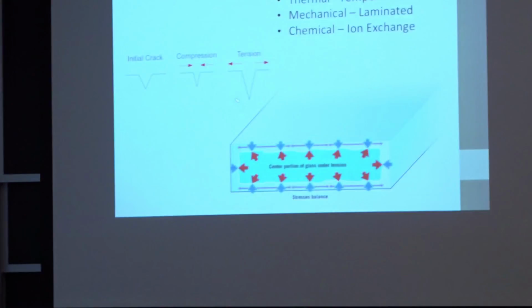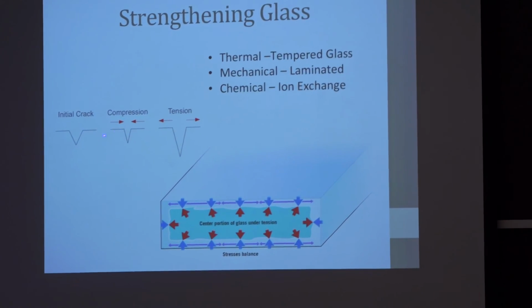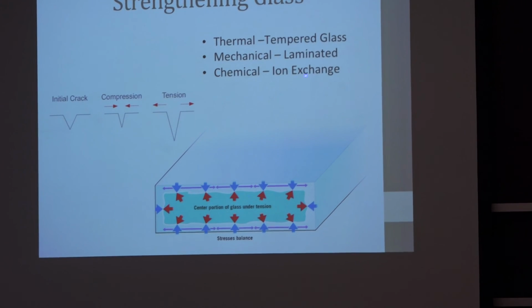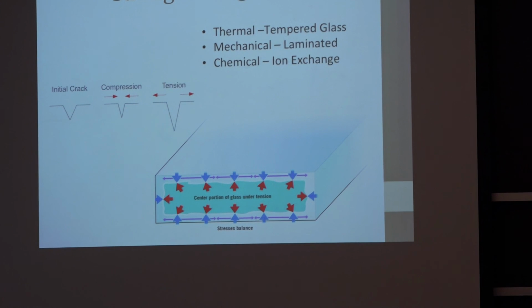I will bet you money this is at least 3 layers. Just like Corning ware, the cookware, it's 3 layers of glass. It's a laminated glass. Top layer and bottom layer like a peanut butter sandwich. The middle layer is going to be a different coefficient of expansion. When you pull these things off like a plate glass manufacturer, just rolls of these sheets of glass, put them together, 3 layers, you end up with, when you cool it down, compression on the surface and tension in the middle. So you can scratch it. You can have moisture attack it, but it's in compression. And when you're in compression, that's what this is all about. If you have compression in your glass, you're going to be stronger, and the critical flaw size is going to be much larger. This is not the critical flaw size, but basically this is laminated glass where you keep the center in tension and the surface in compression.